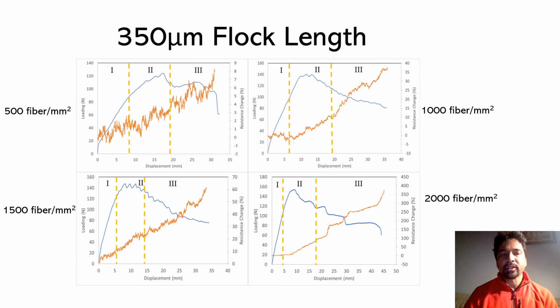Now, coming to electrofracture response, this slide has 4 different pictures, where we are interested only to talk about, in this presentation, 350 microns carbon fiber length, where we have 4 different flock densities, 500, 1000, 1500 and 2000. As you can see, for 500 there is a lot of noise in the electrical response because there is no significant electrical network in the system. With the small flock density of 500, you don't have enough carbon fibers between the laminates. Hence, you are not forming a conductive network within the whole plane of the crack propagation.